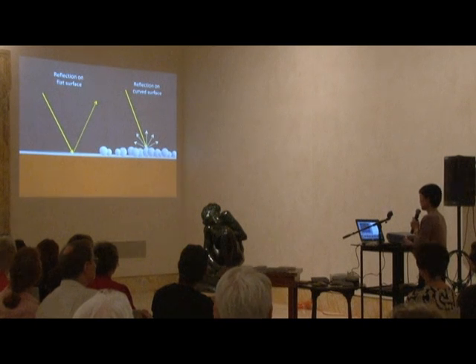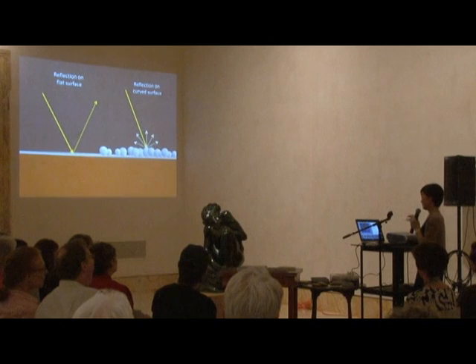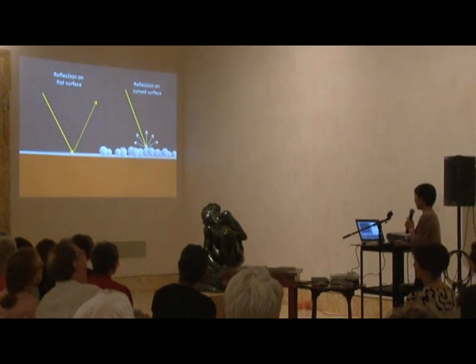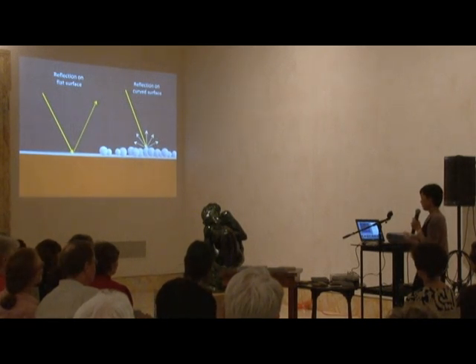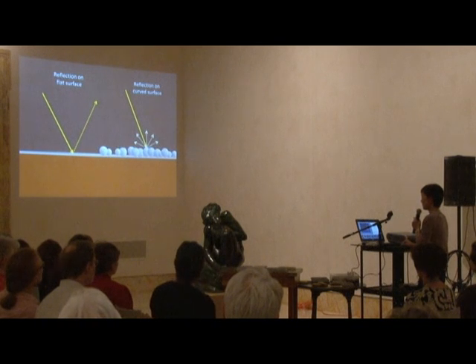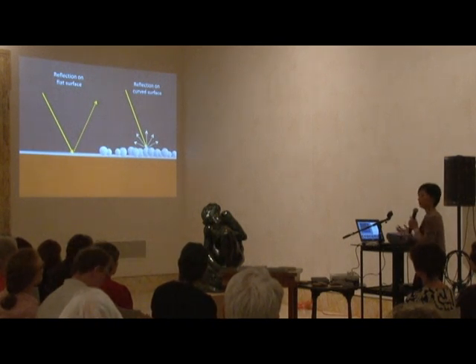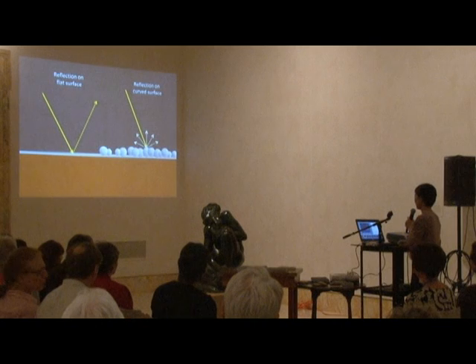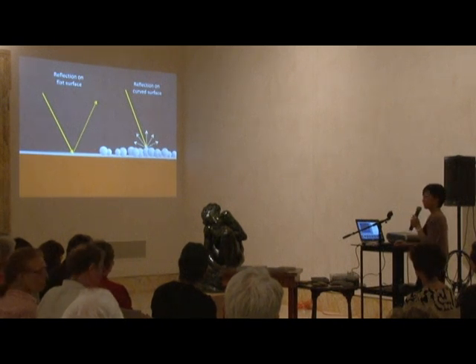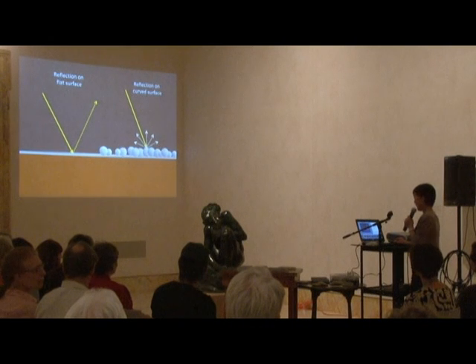These image particles are not embedded in the silver coating, but they're sitting on top. And they're creating topography like water droplets on glass. So the area of image particles appears whitish because of the scattering light. But to make these white areas pop as highlights, you need the rest of the area to be black.